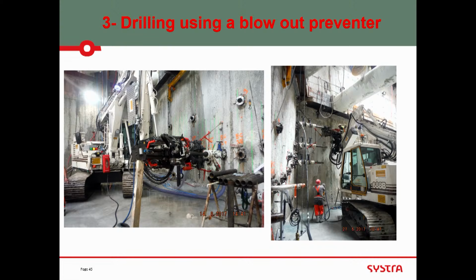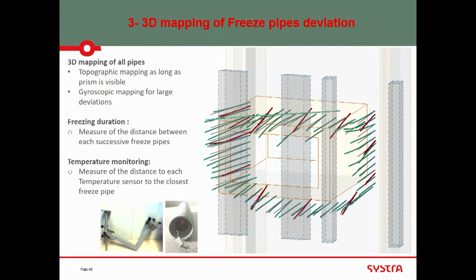So these are the picture of drilling with blowout preventers. This is a full 3D of drilling holes, as well as instrumentation in red. And this is very important to measure deviation, because what is important in ground freezing is the distance between pipes. So if the pipe deviates, the full thermal calculation is done with the real location of each pipe, so that we can at least anticipate the time to be frozen.